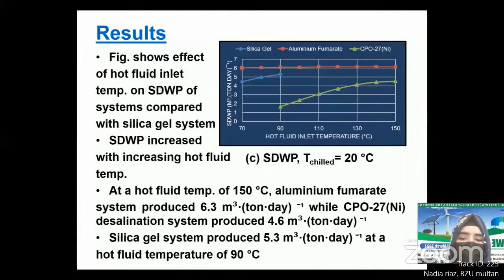The figure shows the effect of hot fluid inlet temperature on specific daily water production of the two systems compared to the silica gel system. The specific daily water production increased with increasing the hot fluid temperature, at a hot fluid temperature of around 150 degrees Celsius. The aluminum fumarate system produced 6.3 cubic meters per ton in a day, while the CPO-27 nickel desalination system produced 4.6 cubic meters per ton in a day. The silica gel system was found to produce 5.3 cubic meters per ton in a day at a hot fluid temperature of 90 degrees.